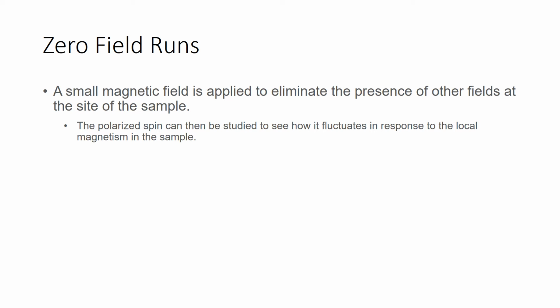To make sure that the muons interacting with the sample and its environment can be specifically studied in the data, zero field runs were used, which means that a small magnetic field was applied to eliminate the presence of other fields at the site of the sample. By doing this, the polarized spin can be studied to see how it fluctuates in response to the local magnetism within the sample, because if there's no magnetic field on the outside of the sample, the muons will go into the sample with the polarized spin, and then once they get into the sample, it can be studied how their polarized spin is affected by the actual sample once they're in it.